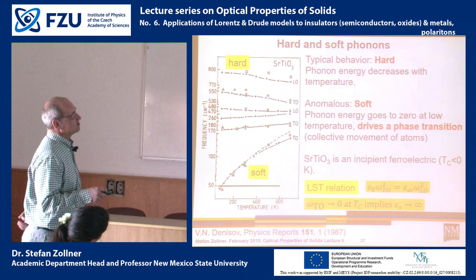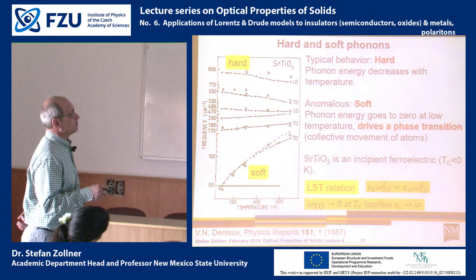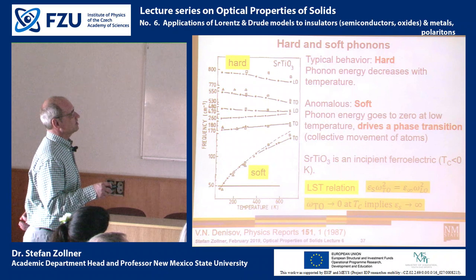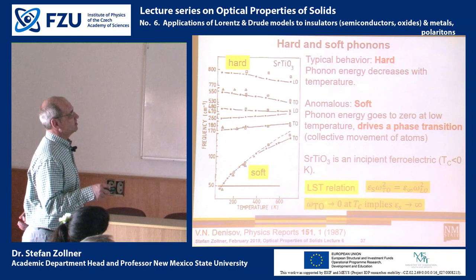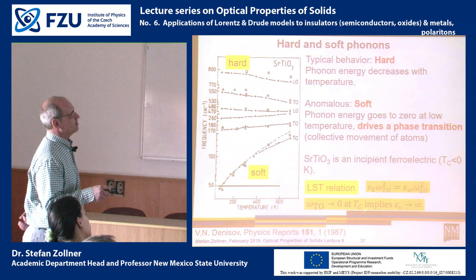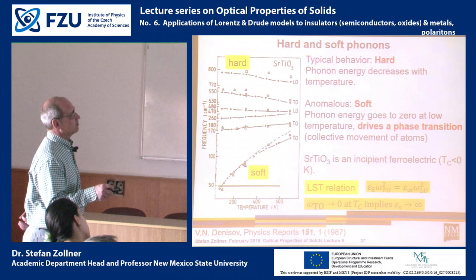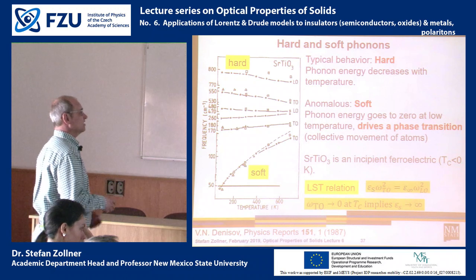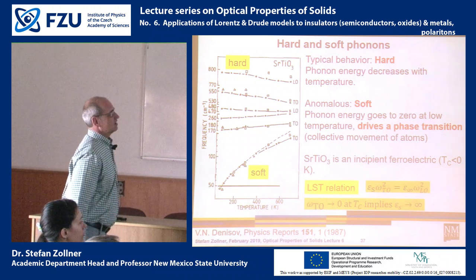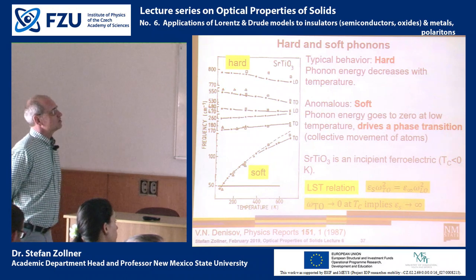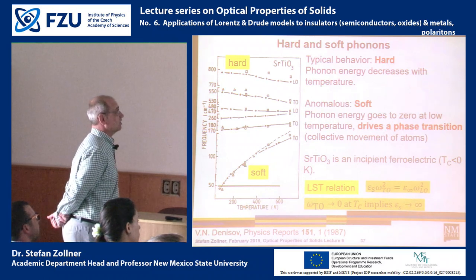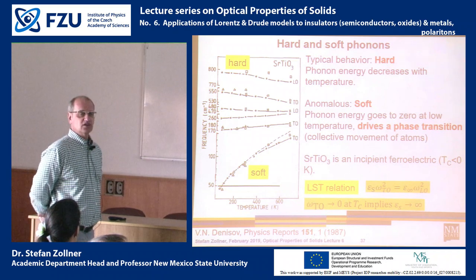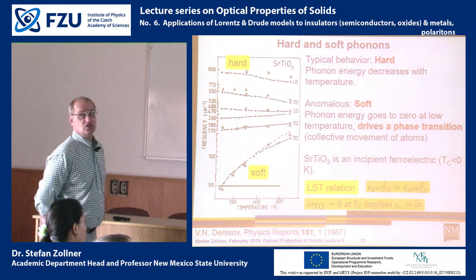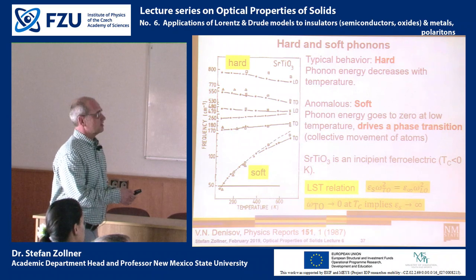So if the resonance frequency goes to zero and we look at the LST relation, the frequency of the TO mode goes to zero at the Curie temperature. So if that is zero, then in order for that product here to remain finite, that means that the static dielectric constant must go to infinity. So such a soft phonon where the resonance frequency goes to zero gives us a transition to a ferroelectric structure.